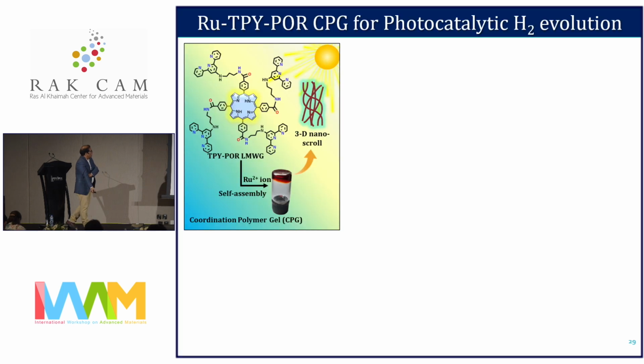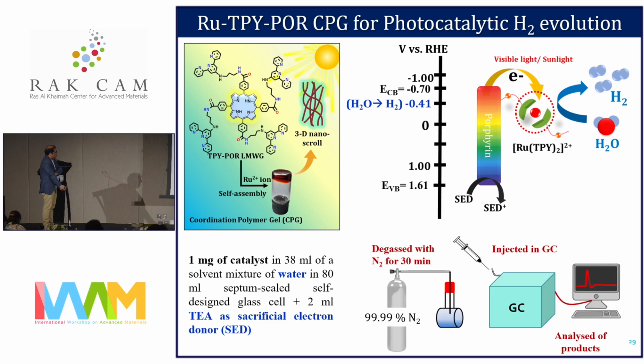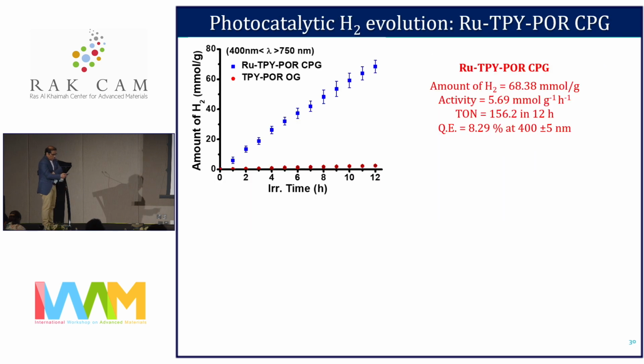Now, in the same system you can co-localize the molecules for photocatalytic hydrogen production. When we tested the ruthenium CPG, the hydrogen production we got in the synthesized CPG is around 68.38 millimoles per gram, with an activity of 5.6 millimoles per gram per hour, and a quantum efficiency of around 8%. But the OG is not active without the metal ion.